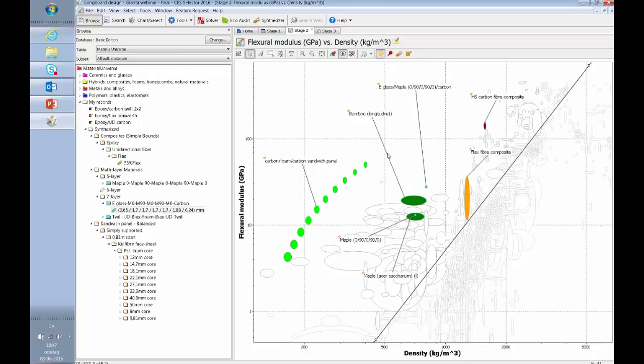I've also plotted the carbon fiber sandwich panel over here. When I looked at this graph, I said, okay, there's definitely room for improvement between these two boards and the sandwich panel here. Based on that, and the materials that we had readily available in-house, we had carbon fiber fabric, and we had flax fiber fabric from working with the cargo bicycle. We measured the mechanical properties, so we knew what the stiffness and the density was of these materials.